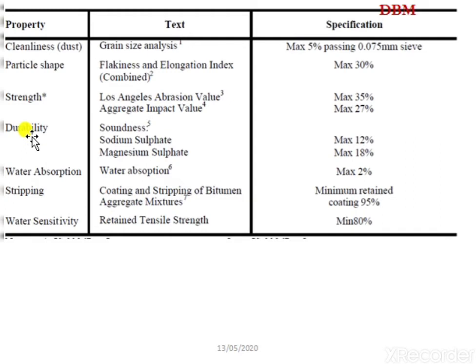The next property is durability. The test conducted to know the durability of the aggregates is the soundness test. The soundness test is conducted using sodium sulfate and magnesium sulfate. When the aggregates are tested using sodium sulfate, the maximum permissible value is 12%, and when tested with magnesium sulfate, the maximum permissible value for soundness is 18%. The next property is water absorption. We conduct a water absorption test on a specimen, and the maximum water absorption capacity of an aggregate should be 2%.